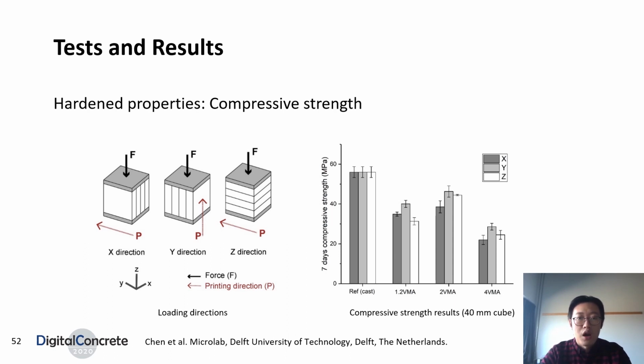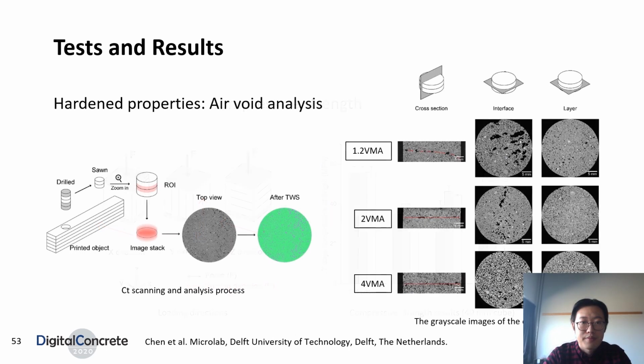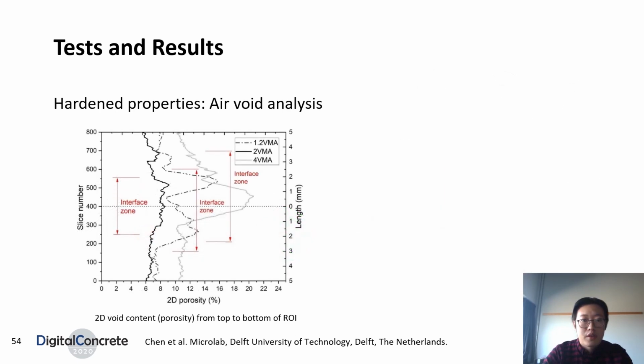To get more understanding about the microstructure of printed samples, we also performed the air void analysis. In air void analysis, the micrographs of printed samples are acquired from X-ray CT scanning. The obtained grayscale images were segmented using the Trainable Weka Segmentation plugin from ImageJ. After processing all images, the results about 2D porosity are illustrated in this figure. Sample 2 VMA showed the lowest 2D porosity, and the highest result is from sample 4 VMA.